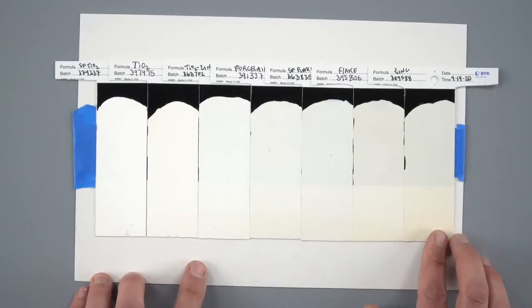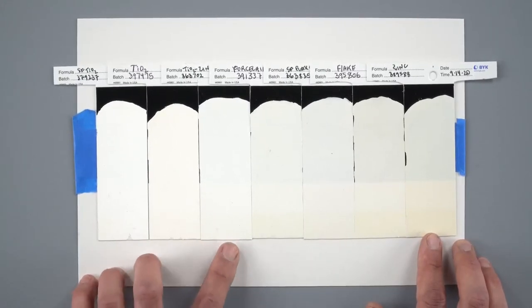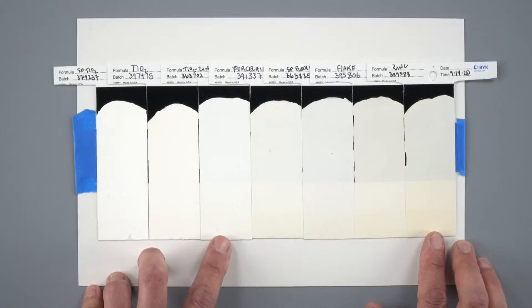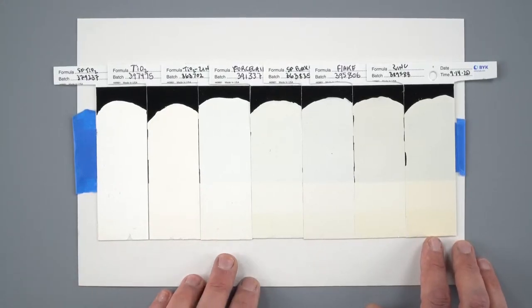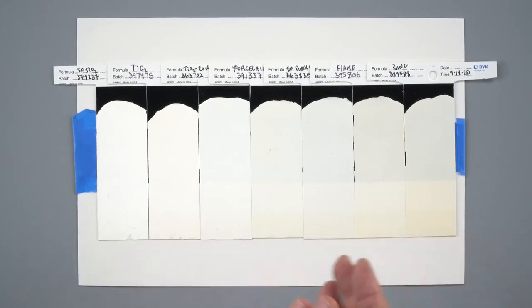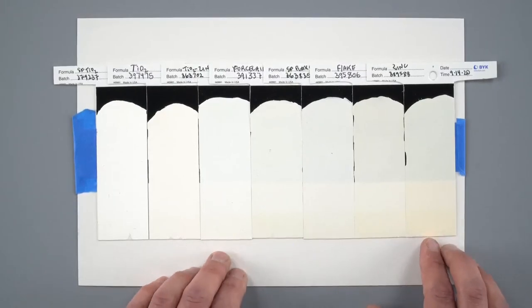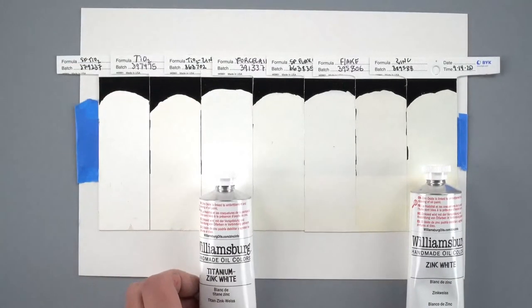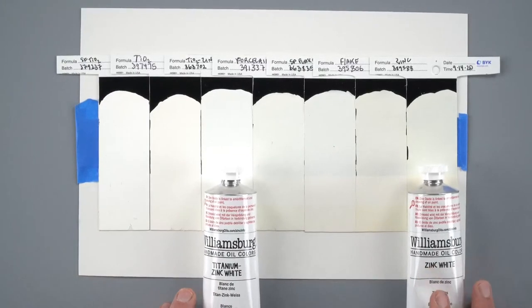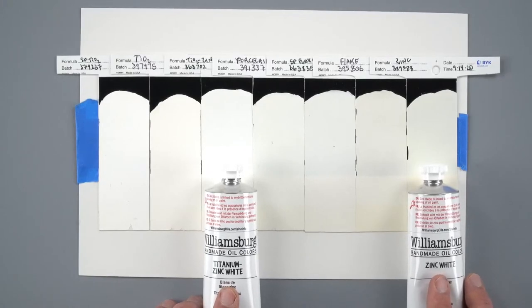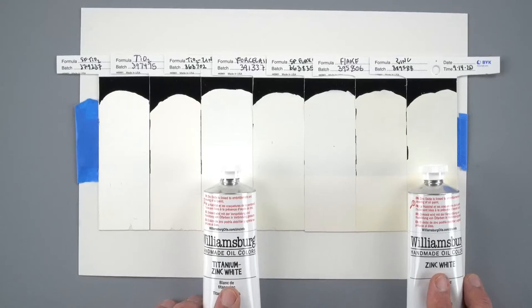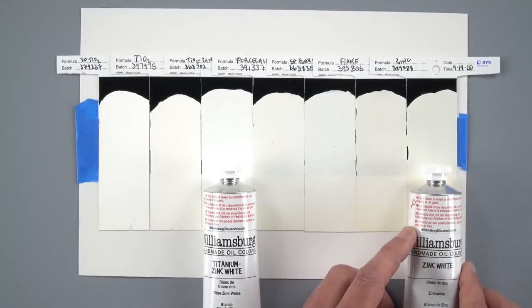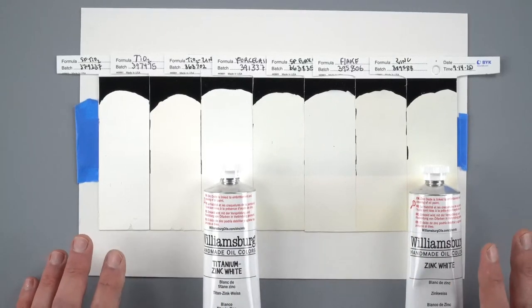Okay, let's talk about a couple things here. While we're talking about zinc, let's put it on the table. Zinc has been found over the years, and it's something that goes way back to the beginnings of zinc, has been known to cause embrittlement in oil paint. That means the paint becomes hard, fast. So it becomes harder much more quickly than most other colors. So the zinc oxide is something that for the longest time we had in our blends. And in about 2018, I think, we decided to take the zinc out of the blends and replace all those whites in those colors with titanium. But we still carry zinc white and titanium zinc white in 150 ml tubes with the warning label on here that says zinc oxide is linked to embrittlement and cleaving of oil paint.